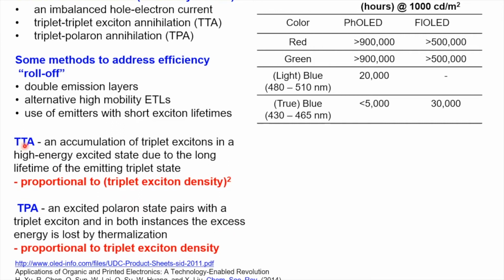In general, triplet-triplet annihilation is proportional to the triplet exciton density squared, because you need two triplets for this process to occur, and triplet-polaron annihilation is proportional to the triplet exciton density. So if you want to minimize these two effects, you need to try and enable the triplets to decay as quickly as possible, so they don't have enough time to hang around and annihilate each other before emitting a photon.